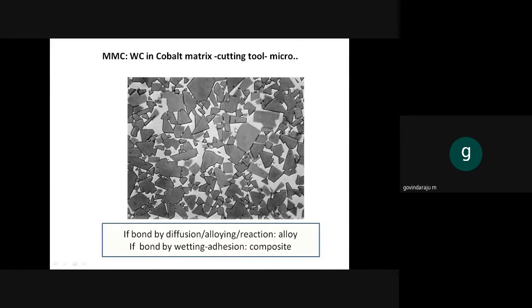So if you want any casting of this cobalt, you have to heat above that melting temperature. But if you want to make any component using cobalt, you make the powder and heat maybe up to 900 or 1000 degrees Celsius, or at best 1100 degrees Celsius. So first is making the powder, second is mixing and blending, third step is called compaction. Compaction is nothing but giving the shape to this mixed powder. What shape you want, that shape, and it should be solid.